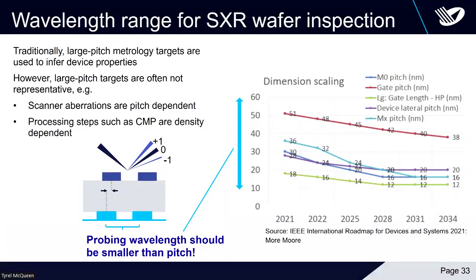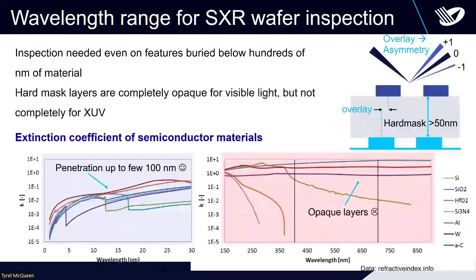And yeah, the main motivation is indeed that large pitch targets are at some point simply not representative anymore. You might measure a good overlay with your 10 micron pitch grating, but that's not the overlay that's actually existing in the device.